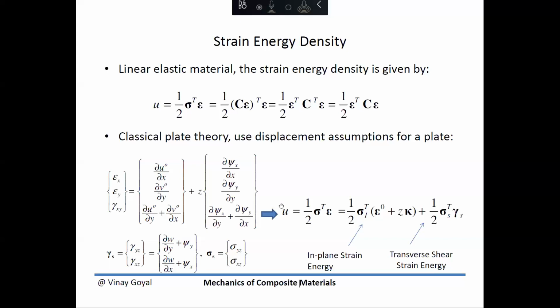And the vector is going to have these strain components, and then it's going to have these strain components. So we're going to have a column vector of 5, these three, followed by these two. And when I distribute sigma bold transpose over the strain bold, what I effectively get is the in-plane stresses are acting over these in-plane mid-surface strains, and then the curvatures, plus this new term that we did not have before, which corresponds to the transverse shear energy term. I invite you to go at home and show that this is what you will get.